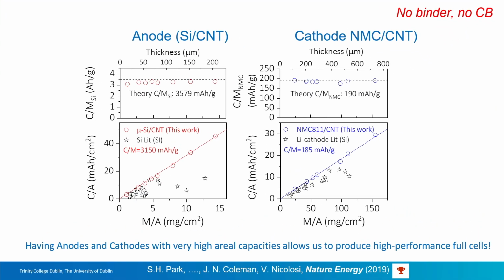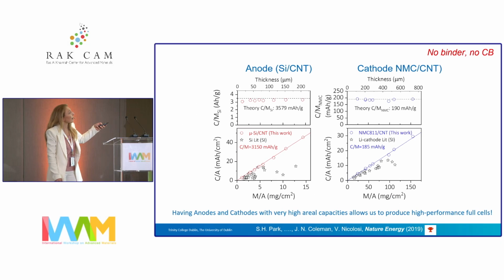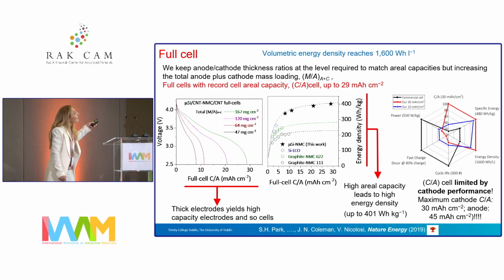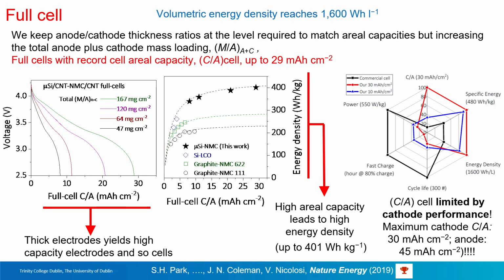We actually tried this method both on the anode with silicon and in the cathode, just taking a very standard nickel, manganese, cobalt type of cathode. And in both these works, we could easily achieve theoretical capacity. So that was quite an achievement. And then when we built the full cell, what we realized is that thick electrodes yield high capacity, and the performance of the full cell is about 6 times above what a conventional battery is capable of in the market. So you get about 29 milliamp hours per centimeter square.